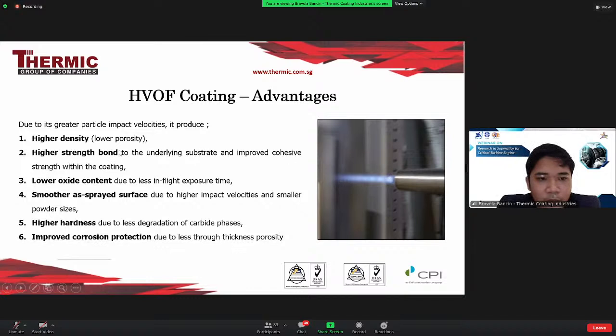And then higher strength bond to the underlying substrate, to improve the cohesive strength within the coating. Lower oxide content due to less in-flight exposure time, because the powder travels from the gun to the substrate in a short time, so the heated powder doesn't have time to oxidize. Smoother sprayed surface, higher hardness due to less degradation of carbide phases. Improved corrosion protection due to less through-thickness porosity.